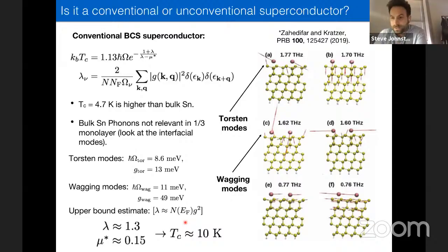Now, again, this is probably not a very reliable estimate, but it at least shows that it is conceivable that the electron-phonon coupling could give you a Tc large enough to explain the data. We don't think this is the case because this mu star treatment is really questionable for a doped Mott insulator. If U is quite large with a narrow bandwidth, mu star is a very questionable thing to use. So we expect that this is probably going to be suppressed in the end by the Coulomb interaction, but at least a priori we couldn't rule it out.